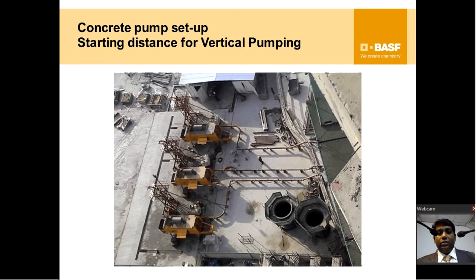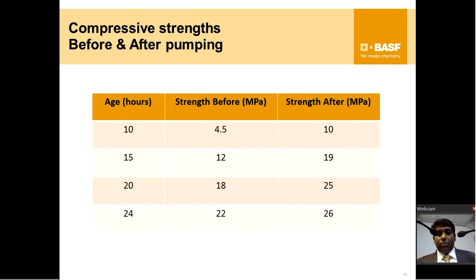Starting distance for a vertical pumping. So a lot of tests were done, at ages 10 hours, 15 hours, 20 hours and 24 hours. Strength before pumping and strength after pumping. You expect the air to be squeezed out of the mix after pumping, so you definitely get a higher strength after pumping as well.